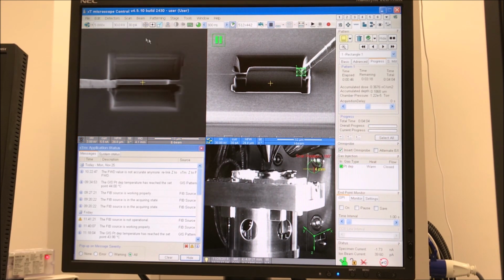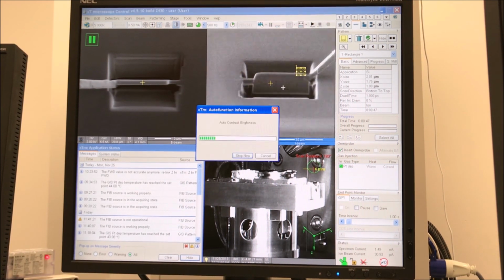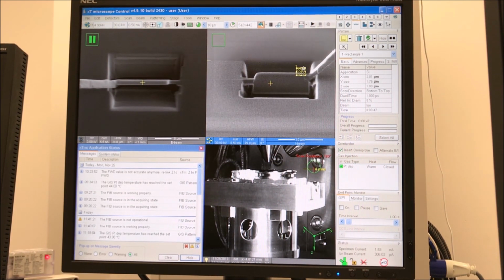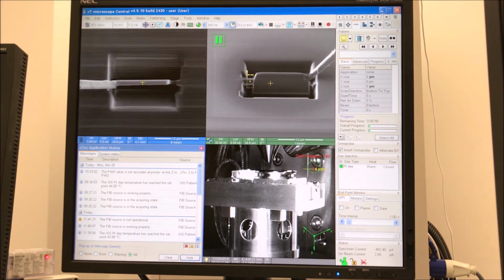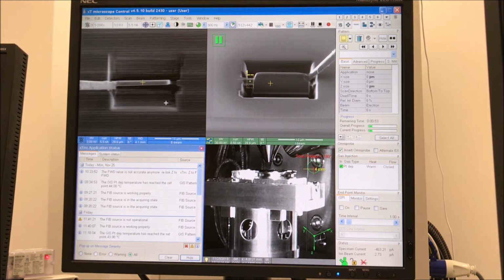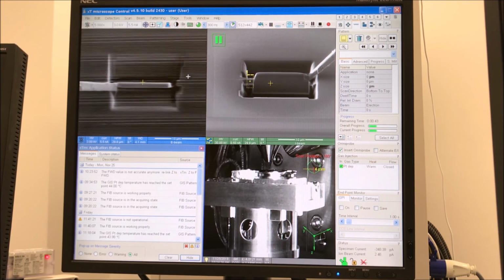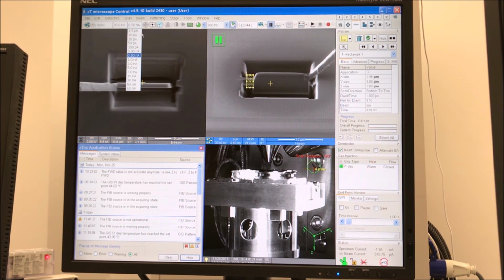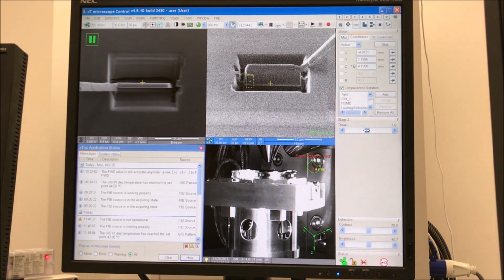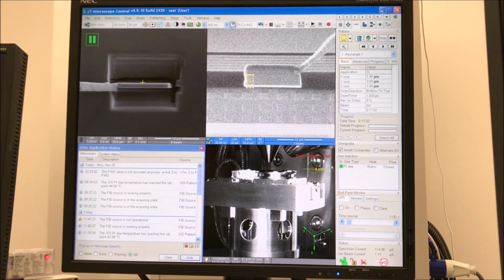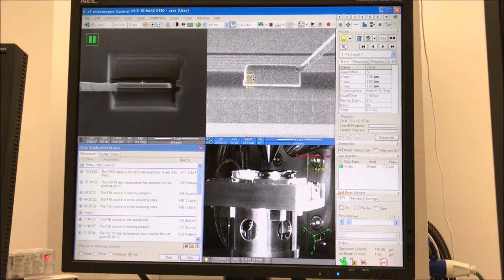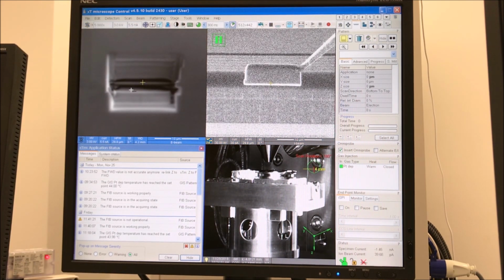So once you have a good weld there, and again, you can kind of just go by feel, you can cut the last point of contact between the lamella and the bulk free. So I increased my ion beam current to 0.5 nanoamps, and I kept the rectangle, but I changed the application to silicon. And so I moved it around the contact point, and now you can see in the E-beam image, once it's been freed, the lamella just kind of flicks off and moves. And now I can separate the lamella from the bulk by moving the stage down, and then I can retract the platinum and retract the omniprobe.